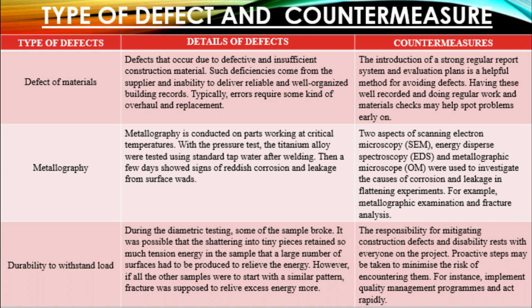Second is metallography. Metallography is conducted on parts working at critical temperatures. With the pressure test, the titanium alloy was tested using standard tap water after welding. Then after a few days it showed signs of reddish corrosion and leakage from surface warts. The countermeasure is that two aspects of scanning electron microscopy (SEM), energy dispersive spectroscopy (EDS), and metallographic microscope (OM) were used to investigate the cause of corrosion and leakage in the flattening experiment. For example, metallographic examination and fracture analysis.